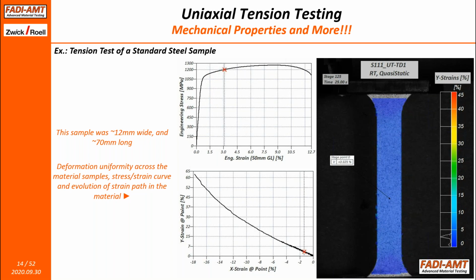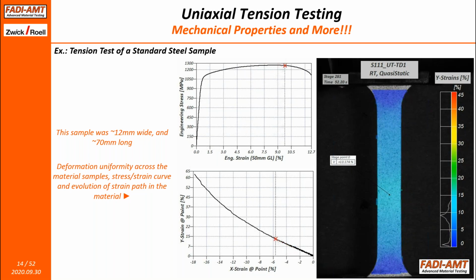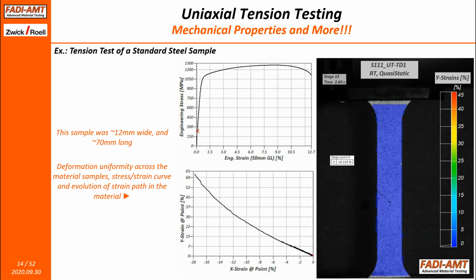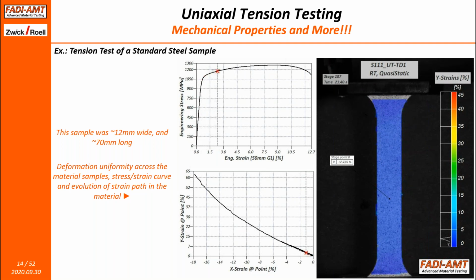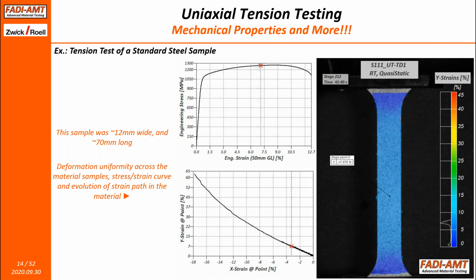Stress strain curve is being developed, and you can see the material is deforming quite nicely, and the stress strain curve looks like a typical steel or aluminum stress strain curve under normal conditions. And of course, obviously, this test can be done by a typical extensometer. No difference, you will get the same stress strain curve. The only advantage here that DIC brings in is the ability to visualize how the material is deforming and where is it failing exactly. And that could be sometimes informative depending on the type of material that we're testing.